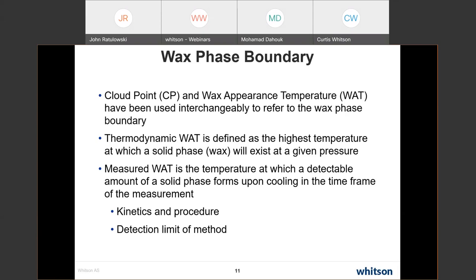The actual thing that we measure, the measured WAT, is a temperature where we see a detectable amount of solid phase forming upon cooling in the time frame of the measurement. So the kinetics and the procedure are important. What rate do we cool this at? That can impact the value of your wax appearance temperature. And the detection limit of the method you're using to measure this is also important.